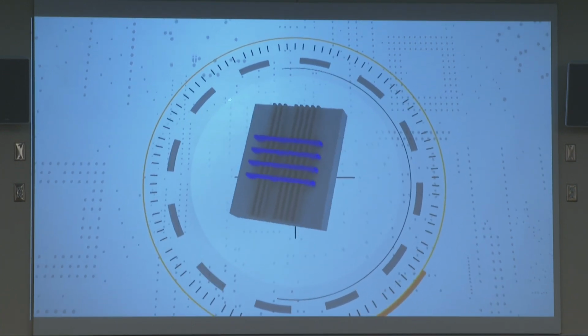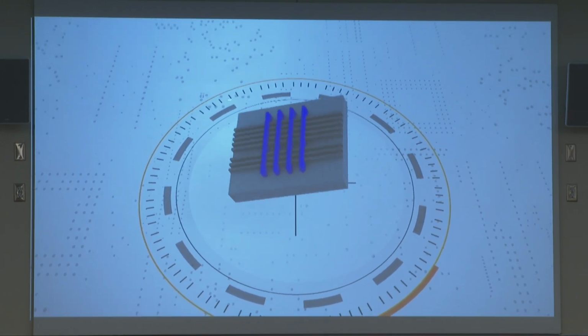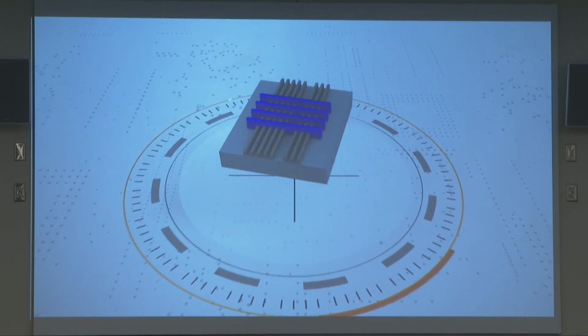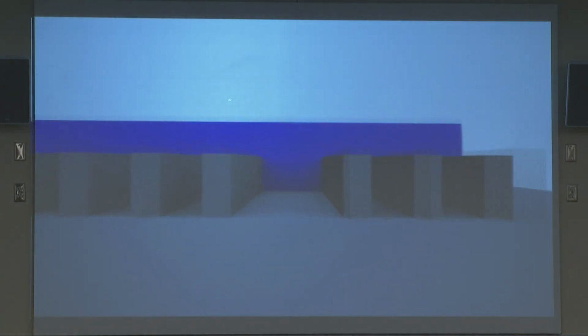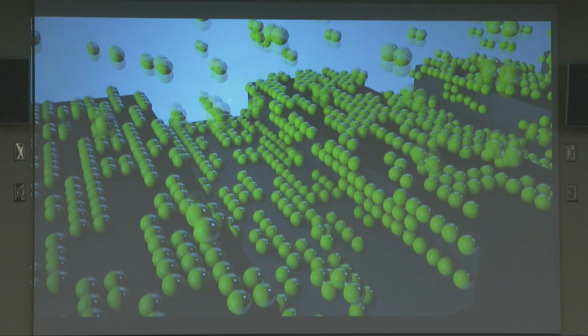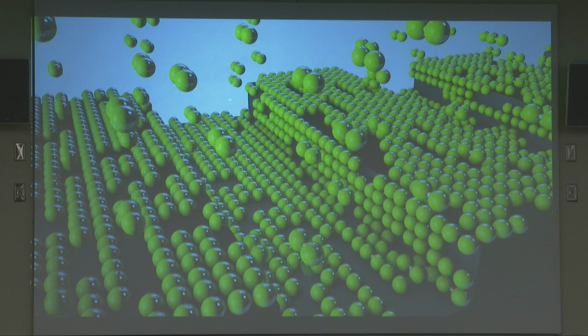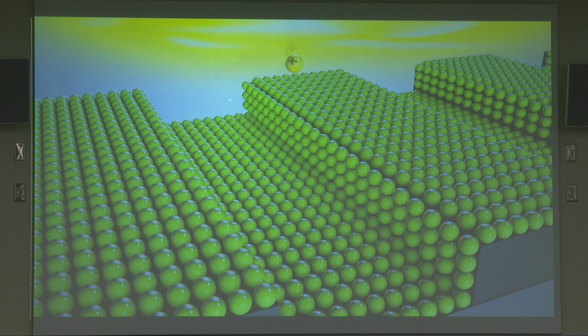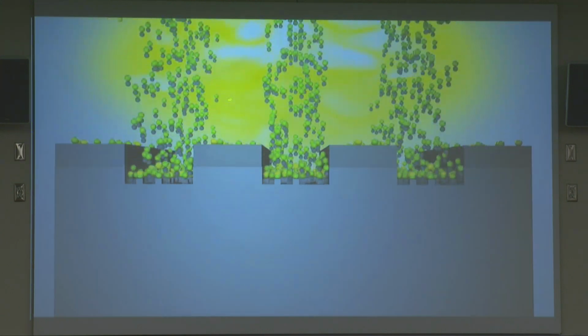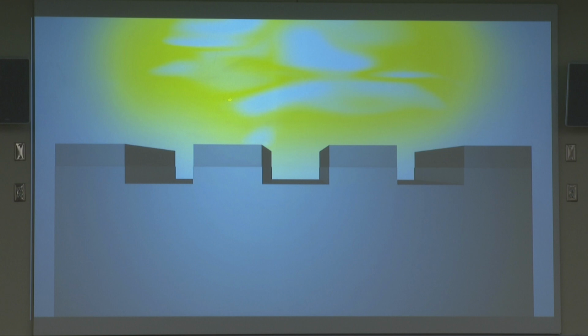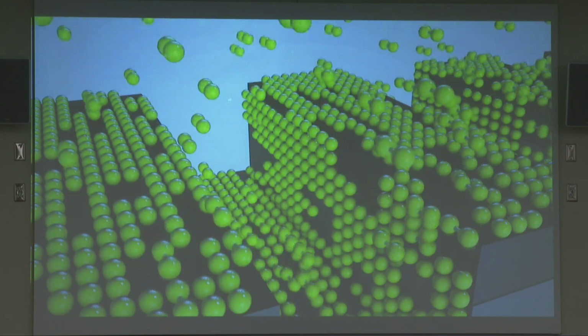Atomic layer etch, or ALE, has been much more challenging to bring from the lab to the fab. It turns out that it is much harder to atomically remove films than it is to deposit them, especially when you need to etch directionally. But at Lam Research, we found a way to make it happen. The ALE process is based on the same concept as ALD in that the reaction steps are separated. ALE typically starts with an adsorption step to form a reactive layer, followed by a removal step called desorption to take off this layer. Using ions allows for the directional etching required to form deep, narrow structures.